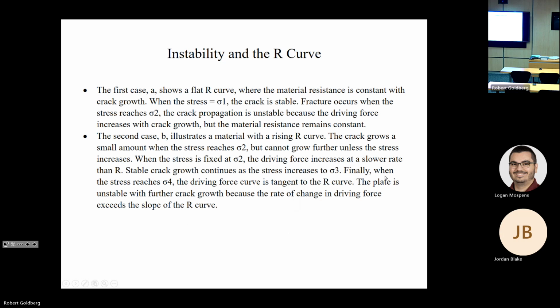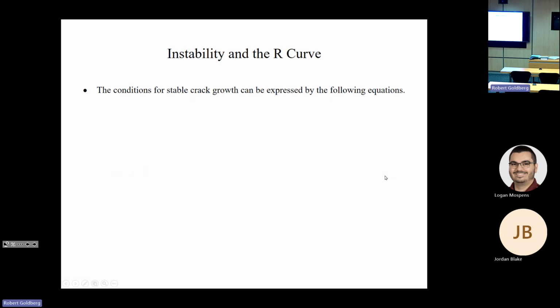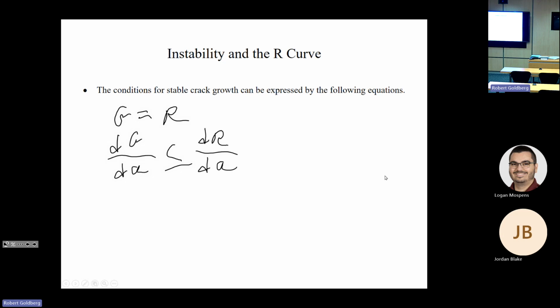Okay. And in words, that's all this is, which I just said. So the conditions for stable crack growth can be said as follows: when your strain energy release rate is equal to your resistance, it's stable. And when the rate of increase of your strain energy release rate, your driving force, is less than or equal to the rate of increase of your resistance as a function of crack length.